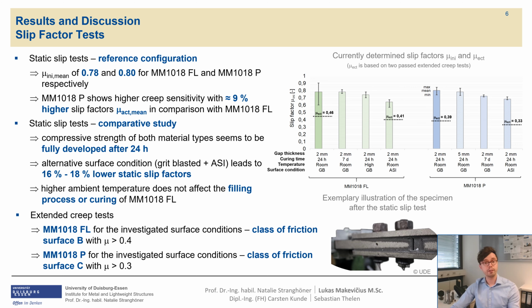Finally, the first extended creep test showed that slip factors of more than 0.4 can be achieved by using the liquid type of the gap filling material MM1018 for the investigated surface treatments. This corresponds to class of friction surface B according to Eurocode 3 Part 1.8 or the EN 1090 Part 2. The pasty type of MM1018 leads to lower slip factors of 0.33 and 0.38, which can be attributed to a higher creep sensitivity of the material. These results comply with the class of friction surface C according to the standards that I mentioned before.